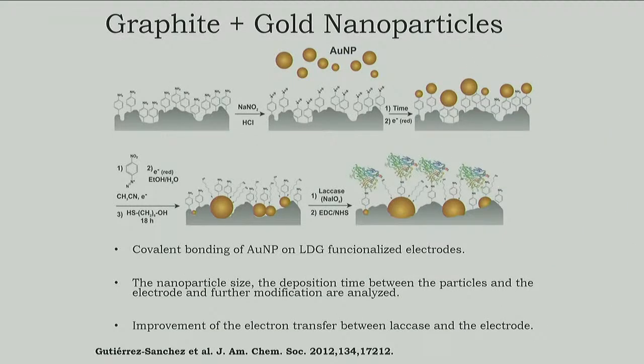Another line of work is to modify the graphite electrodes with gold nanoparticles. We have been using, in this case, two different sets of gold nanoparticles of different sizes, one that is on average 16 nanometers and the other 5 nanometers. The strategy to immobilize the nanoparticles is similar to what we use with enzymes.